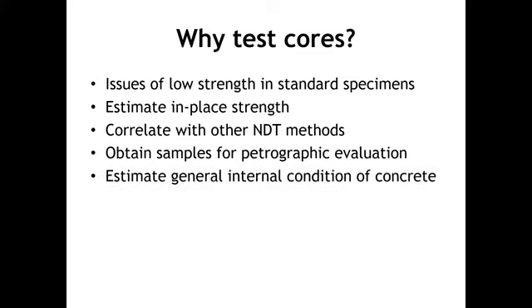So this test is very simple, and this gives you the pH value of the concrete. So for this particular case, your carbonation depth is about 40-45 millimeter. If I simply remove only 25 millimeter, I get a sound concrete, and then if I leave it as it is, again, that's not going to be the right methodology.